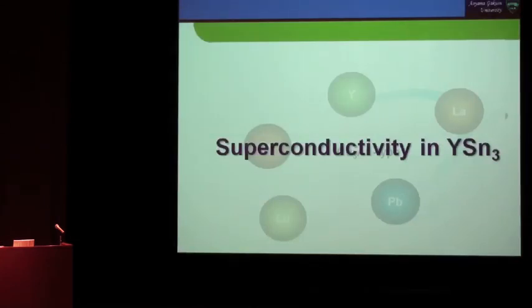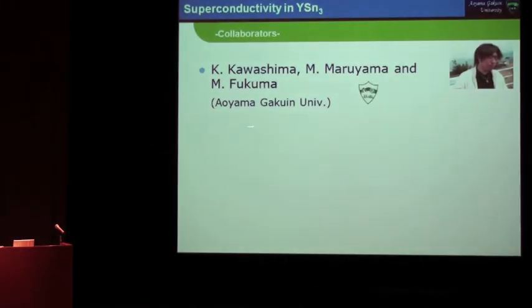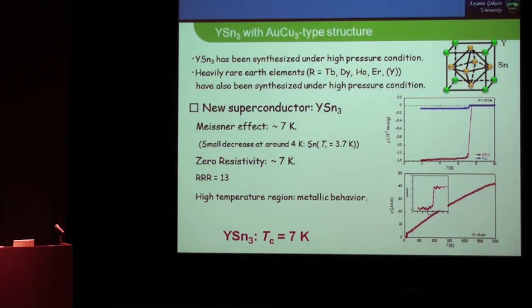Next, last topic: recently we found superconductivity in yttrium tin-3. We believe this was discovered by Kawashima. We briefly mentioned that the YSn3 system, yttrium tin-3, is AuCu3-type structure, and superconductivity appears at TC equals 7 Kelvin, with the high temperature region showing metallic behavior.